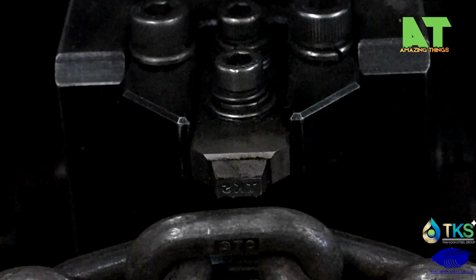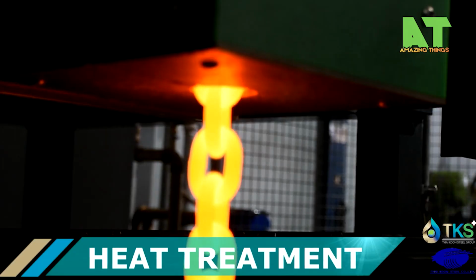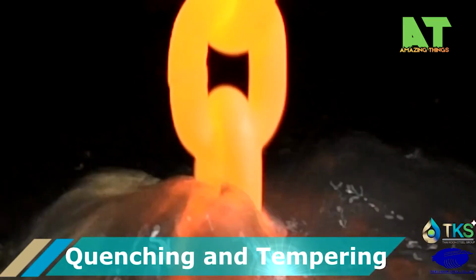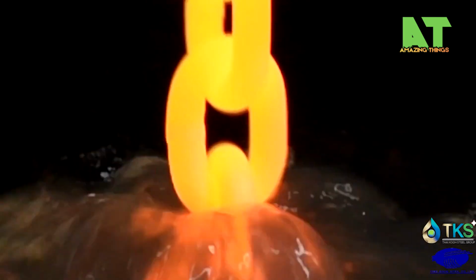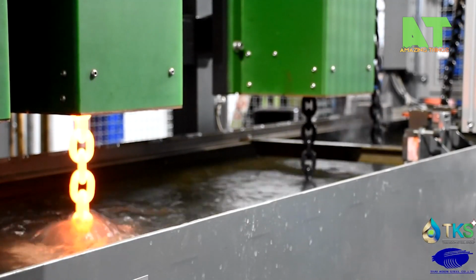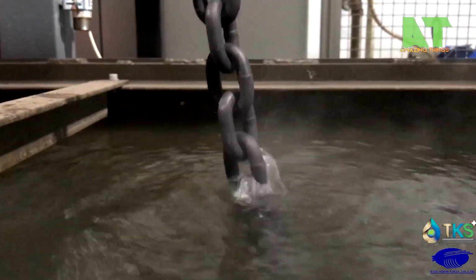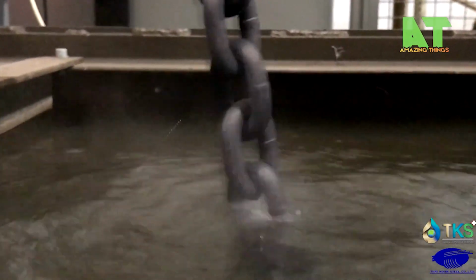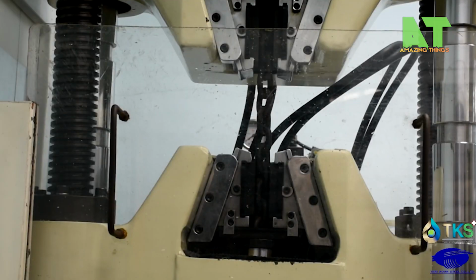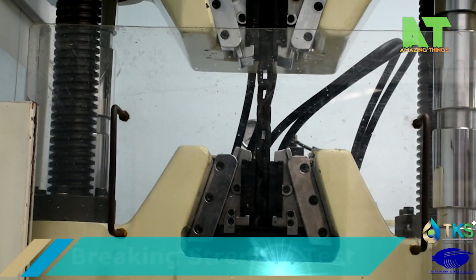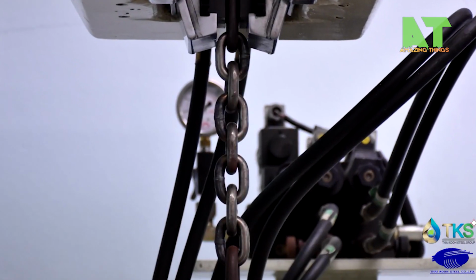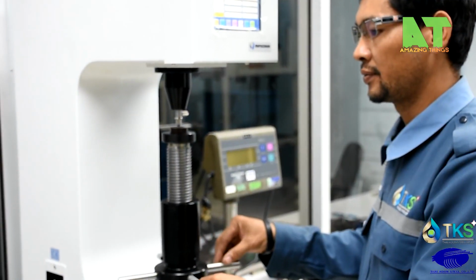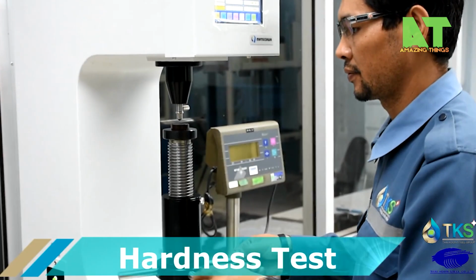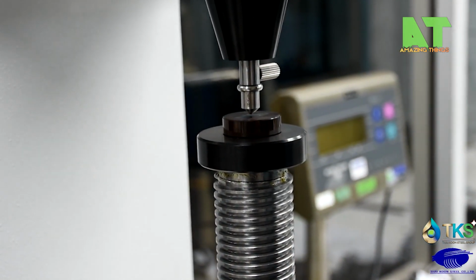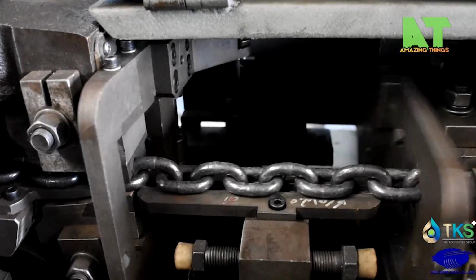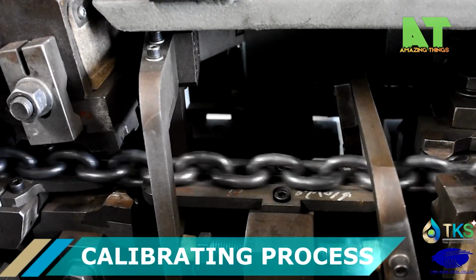Each new link is formed around the previous one, mechanically interlocked before it's even closed. The forming machine positions the bent wire segment so that it passes through the opening of the last completed link. Then the ends are brought together, and we move to the next step. For welded chain, the open ends of each link are joined using electric resistance welding, also known as flash butt welding. Two copper electrodes clamp onto the link ends, and a powerful surge of current generates intense heat at the contact point. The metal becomes semi-molten in milliseconds, and a controlled force press fuses the ends together. The weld is then trimmed smooth, leaving a joint that's often stronger than the surrounding metal. For non-welded chains, the ends are simply pressed closed under extreme mechanical force.